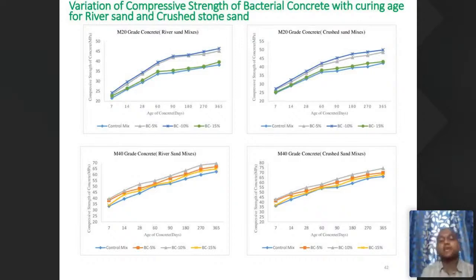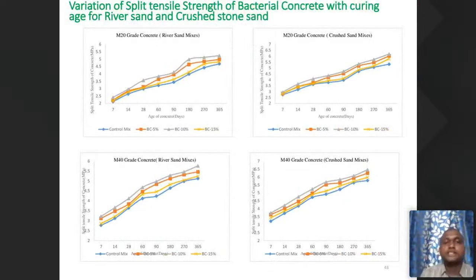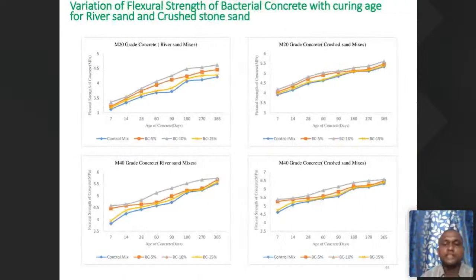Why does the strength increase? Whenever bacteria or calcium lactate are added to the concrete, the permeability of that cube or structure is reduced. Whenever the permeability decreases, there are no voids. Definitely the voids are not there, so there is a possibility of increased compressive strength. In our research too, for the two grades, there is an increase in strength. Likewise, the split tensile strength also increased from 7 days to 365 days, especially for M20 and M40 grades, with replacement of fine aggregate. While we use river sand, here we also use crushed stone sand, that is nothing but M sand.